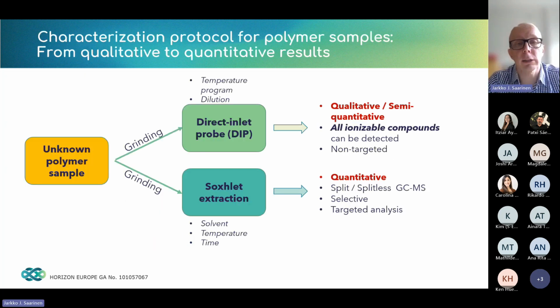So the characterization protocol for the polymer sample. If we receive an unknown polymer sample, what we typically do is a cryogenic grinding, and then we use our direct inlet probe together with the timsTOF device. And what we can gain is qualitative data and also semi-quantitative data of the different compounds that are present in the sample. This is suitable for all ionizable compounds. They can all be detected, and this is also suitable for non-targeted analysis.